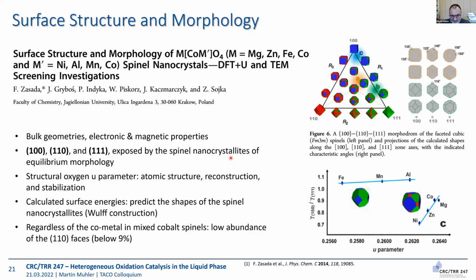Now the question, what can we do about it? I think you have also read Zbigniew Sojka's literature, as it's kind of overwhelming. He's publishing high quality papers every year, and he has established, nice name, a morphodrome of all the spinels. And the question is then, of course, when we have these more or less spherical nanoparticles, like shown here, that would be the cube octahedron, then we expose all kinds of facets. Is it possible by changing the relative amount of exposed facets to tune the reactivity of our nanoparticles? So that was the idea behind it. So can we have, for example, more of these 110 facets?